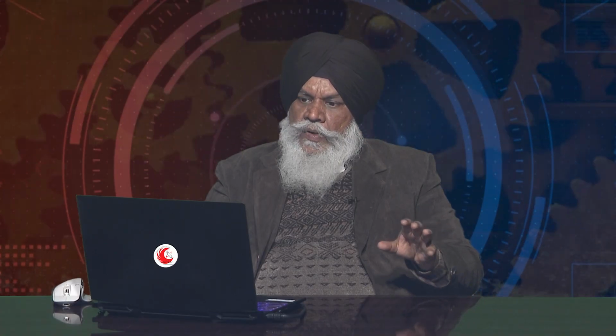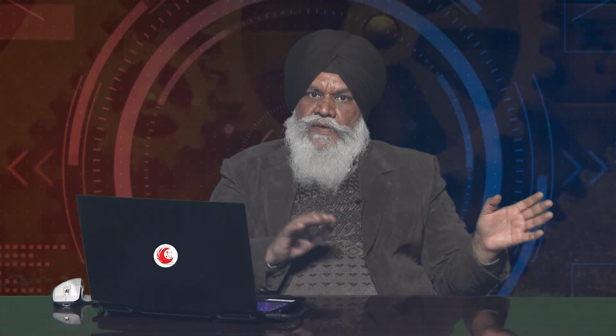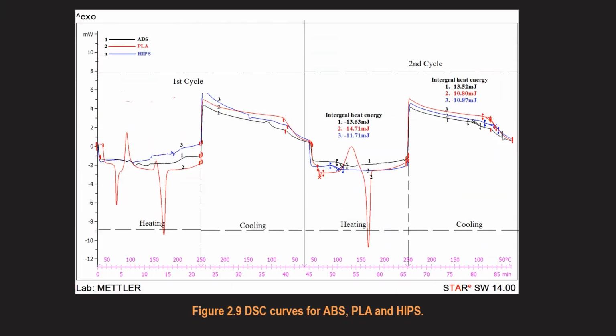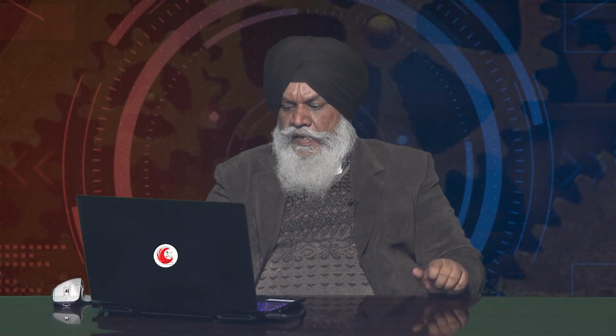Before going to actual mechanical property, we try to see their variation in the thermal properties, like I have explained in my previous lecture that we are interested in their thermal analysis, like which material is stable, which is not. You can see in this case for the ABS, which is represented by a black line curve, in the heating cycle as well as in the cooling cycle, the energy absorbed and released is almost in the same range. Whereas if I go for the HIPS, you can see there is a variation in the energy absorbed, and specifically for the PLA there is a large deviation. That means PLA is relatively less stable thermally as compared to the other two. So to put the point that their mechanical properties are different, their thermal properties are different, and what happens when I am using this type of hybrid structure.